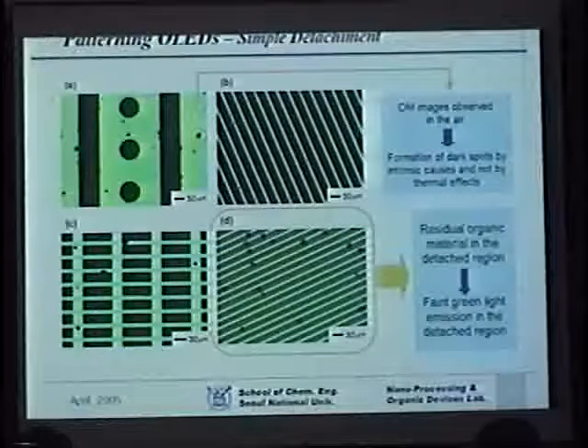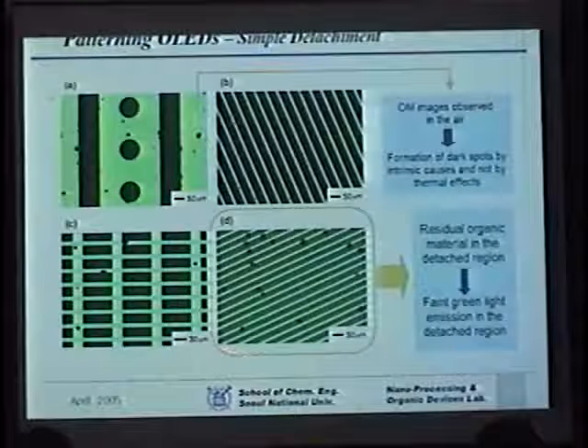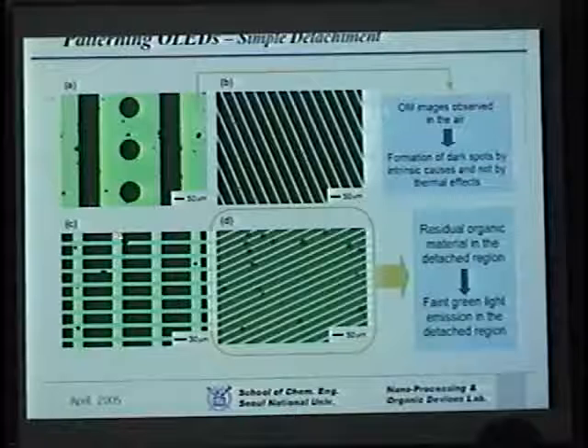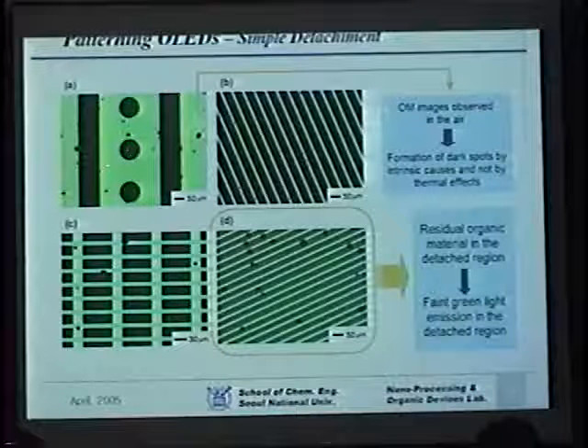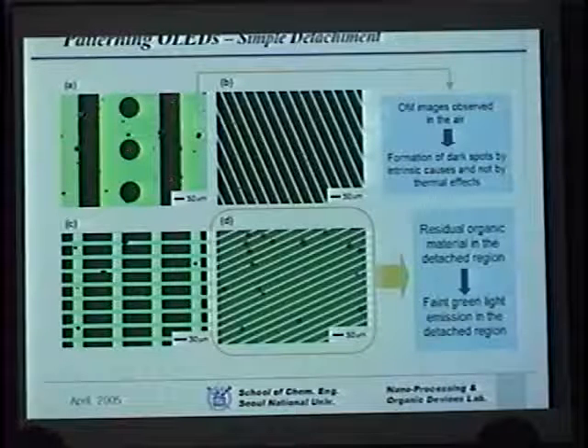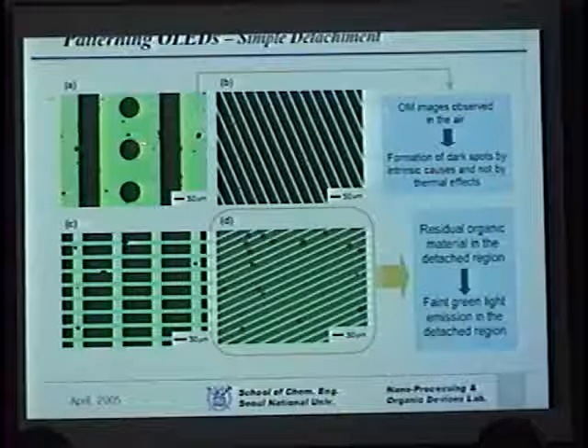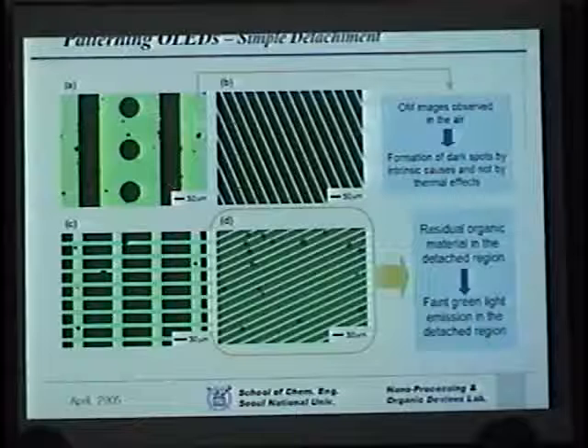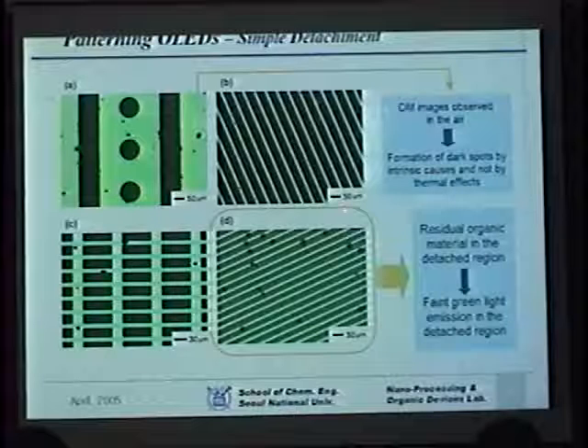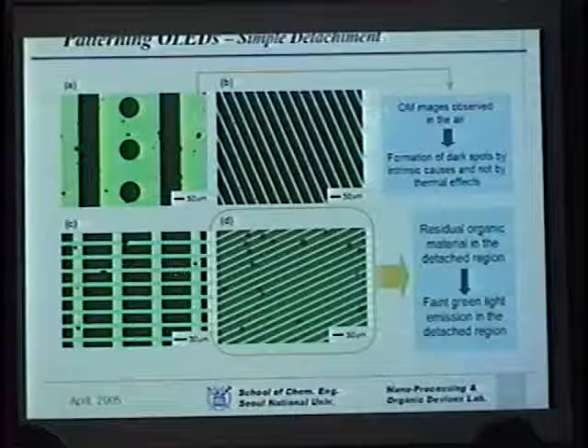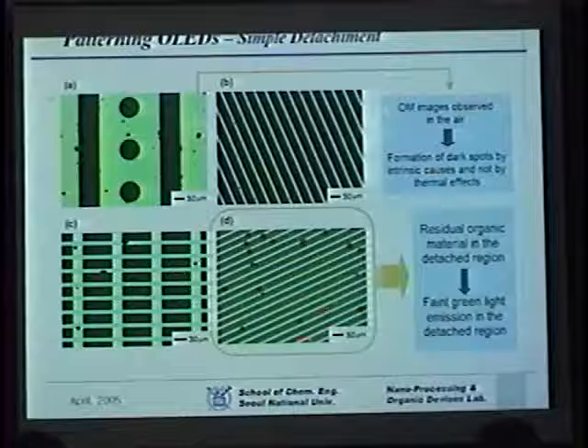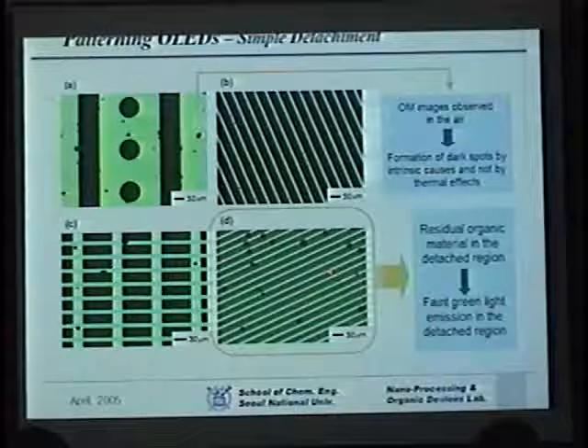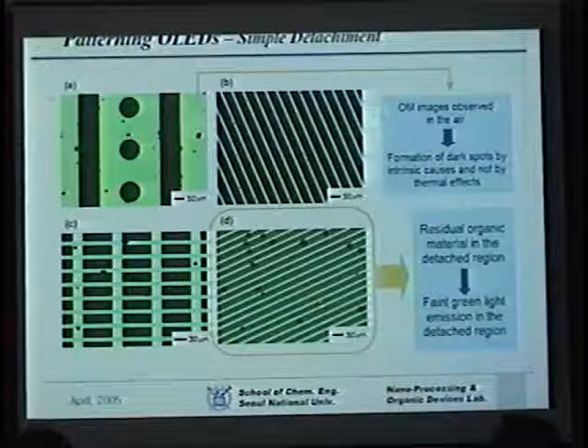So we also wanted to show that it works with the device as well. That is, when we apply that technique to fabricate the device, the result would work properly. In this particular case, in this part, the NPB, and we use an Alq3 active layer, and Alq3 is missing here, so no emission. And so you can see green emission, also line pattern, light emitting through line patterns. This here is the sort of grid structure. But if you do not do a good job of detachment, there's some residual layer remaining, and so you have a smearing effect.